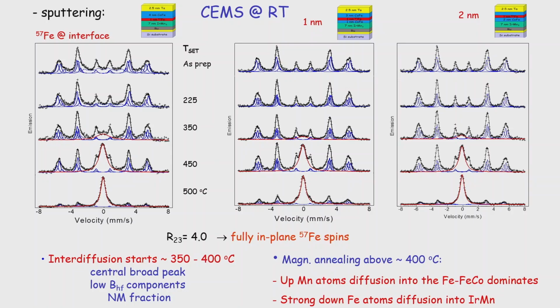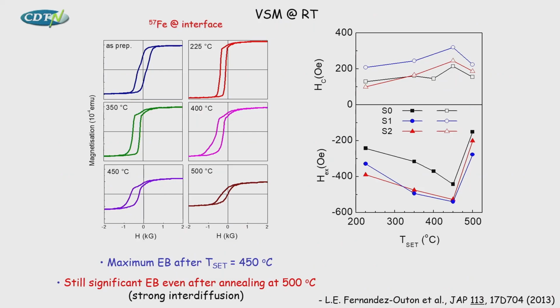Okay, understood. Because what I see is the behavior where you improve the exchange bias up to 400°C, and after that you have another behavior. You are really killing completely the magnetic phase. Yes, that's the magnetic measurement. But you see that in the loop the amount of magnetic material is decreasing a lot.